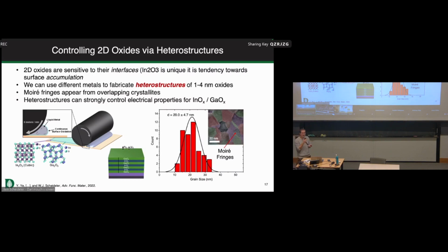We can exploit that effect, though, even further if we develop heterostructures where we stack other materials on top of it. And this idea, in some sense, comes from traditional semiconductor devices. There's an effect known as modulation doping in the III-V community, where you actually use a wider bandgap material at the interface with the narrow bandgap material to change its electronic properties and to induce some high mobility transport in the channel. Now, the advantage of doping it with a heterostructure compared to doping it extrinsically is that traditionally you can maintain more efficient electronic transport, right?